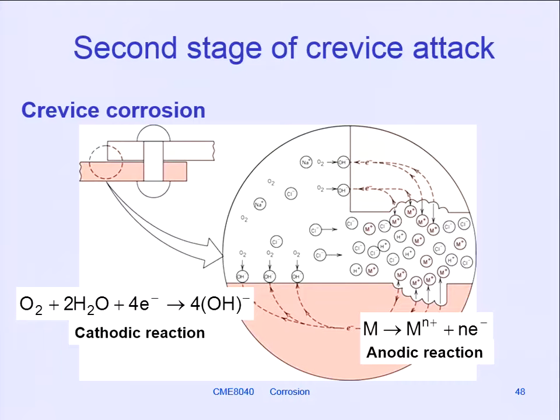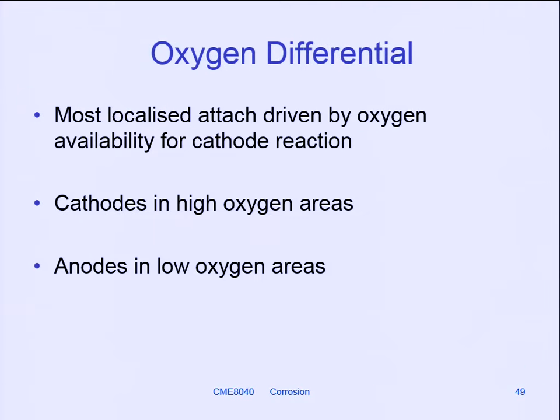So that was the crevice corrosion. There's the oxygen reaction at the cathode, using up oxygen, and new oxygen has to diffuse to the cathode, and it has trouble diffusing along a long path. So if you've got a crevice, diffusing it all the way into the crevice is quite difficult. So the cathode reactions come out to the high oxygen area instead. Oxygen differential, and this drives the pitting corrosion, crevice corrosion, stress corrosion. It drives a lot of corrosion mechanisms.